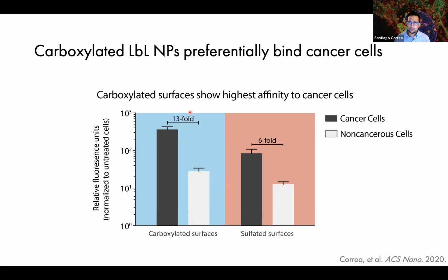What we can see in this simplified chart is that carboxylated surfaces are mediating the highest amount of nanoparticle accumulation on cancer cells compared to sulfated systems. And then the differential between cancer cells and healthy cells is also greater when we look at these carboxylated surfaces, 13-fold specificity over 6-fold specificity. So that was a promising indicator that we're going to see some interesting formulations emerge from the carboxylated family that might be exciting for more downstream development. And so I want to take us down a step further.